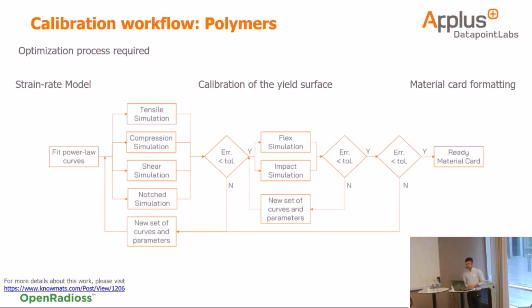So for this complex material model, which is SAM for polymers, first of all, it's not recommended for reinforced polymers, but this is something that we are already doing with reinforced polymers, so we can achieve a process on how to calibrate for reinforced polymers with more or less good success. So we use an iterative process where optimization is required.